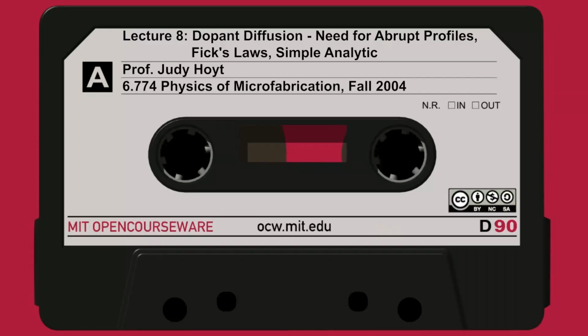Now if we look on the right, in semiconductors or in silicon, we typically don't have a cube or a chunk of material. We're usually measuring the resistance of a thin sheet in the near surface region. And that sheet generally has dimensions, length and width, that are much larger than its thickness. So if we have a shallow junction, as pictured on the right, we can calculate its resistance as follows. Again, using the same formula, it's the resistivity in ohm centimeters times the length, now divided by the area.